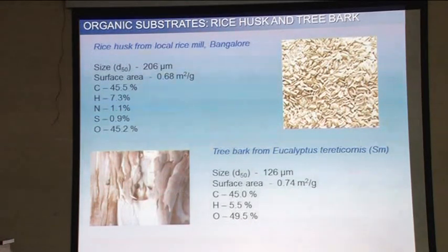That is, we have taken here the rice husk as well as the tree bark. We have characterized the waste. And when we treated the acid mine water obtained from the Chitradurga mine, we could see that we could easily get complete removal of iron, both in the ferrous and ferric state, as well as the concentrations of copper and zinc were below 2 ppm.